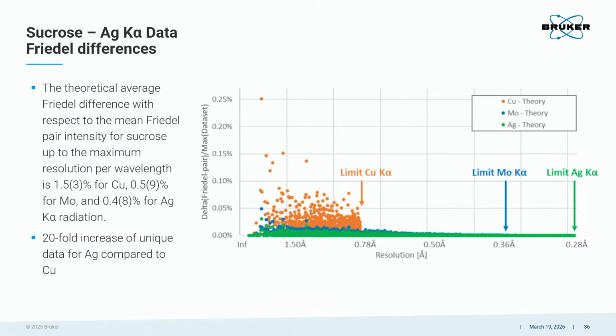And it's very interesting. We thought hard about that, and there's a researcher in Spain, Jordi Benet-Buchholz, who has done a lot of work on moly. Basically what it comes down to, and I mentioned this before, is the 20-fold increase of unique data for silver compared to copper. This is what makes it possible. The interesting thing with the resonant scatter, the anomalous signal, is that it stays pretty much constant over the whole range in 2 theta. And that is very important.